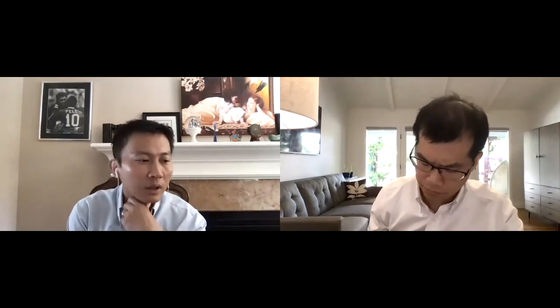voids. Stripping can cause significant non-uniformity right there, and your SEI won't be as uniform. And then the stripping coming in causes the void formation, which we tend to see the pit formation easily. So stripping, I would say, is equally important as deposition, so we shouldn't overlook it.